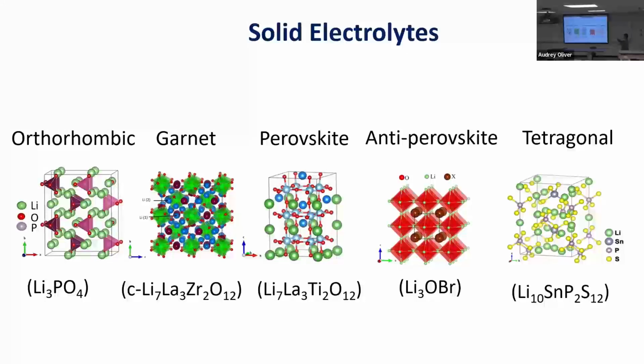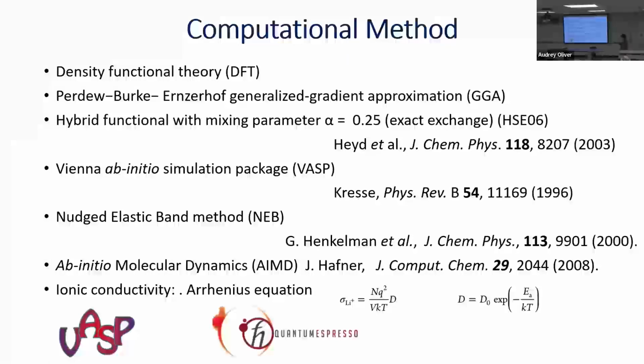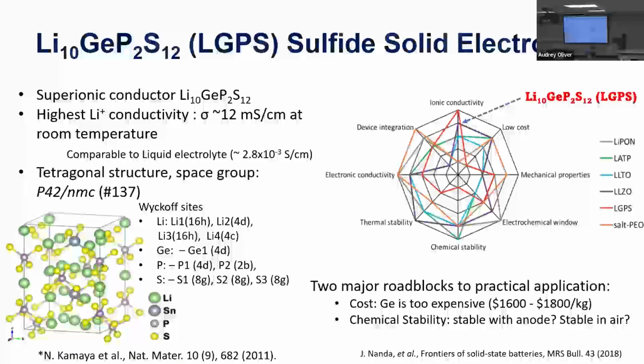pathway. Once we know that, we know how to align with the electrode. If it is the G direction, then we align with the electrode. So we can do this kind of design after understanding from first principles. With DFT, using those packages, for the barrier we use the nudged elastic band method. We can use molecular dynamics to get diffusion coefficients, and we can calculate ionic conductivity after getting the diffusion coefficient. Once you know the activation energy, we can get all this. Okay, so for battery,